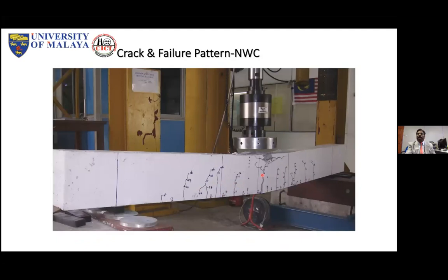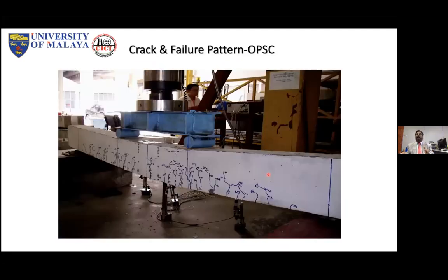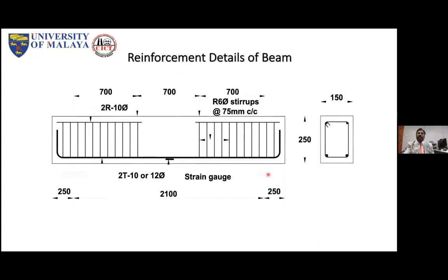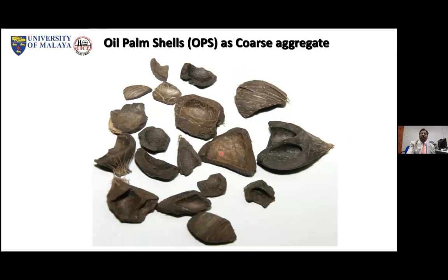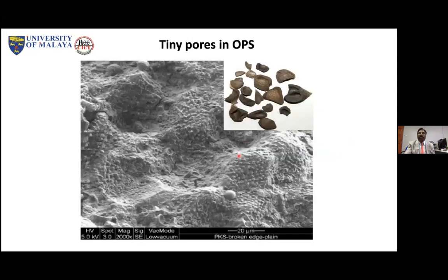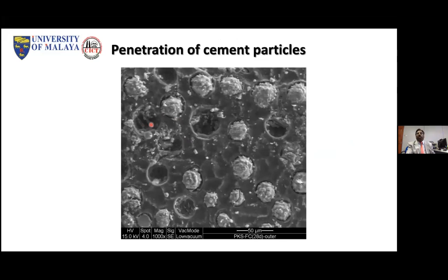What does it mean? That means the concrete has good bond characteristics, because it has a concave and convex surface. It's a good question, and very important for everybody to understand. You have a concave surface, a convex surface, and a broken surface. All three surfaces behave differently. When you mix in the concrete, on the broken surface there are millions of tiny pores. These tiny pores have a size of 20 to 30 micrometers, and you are filling those pores.